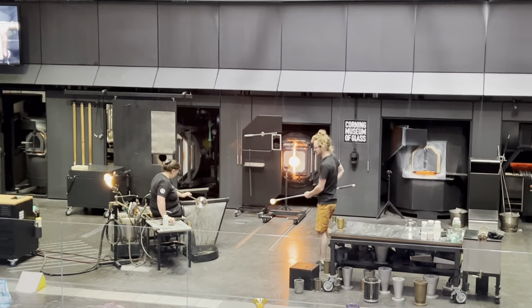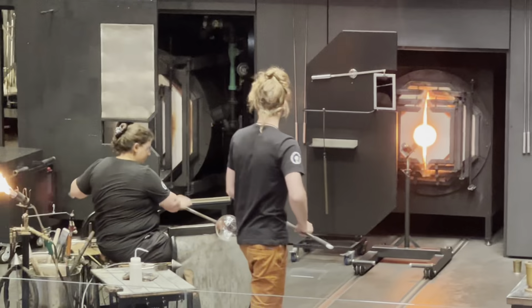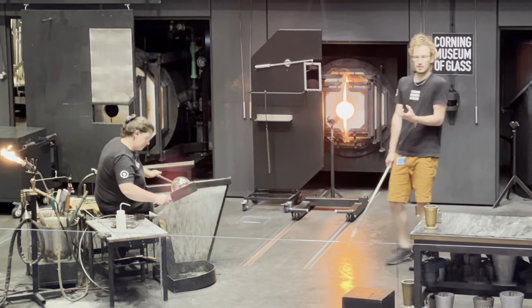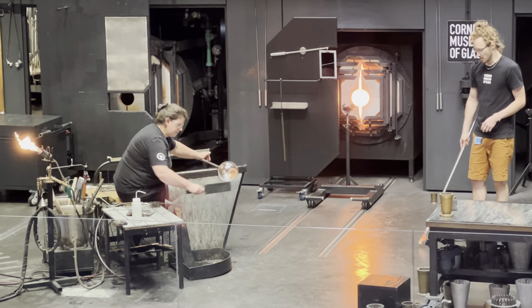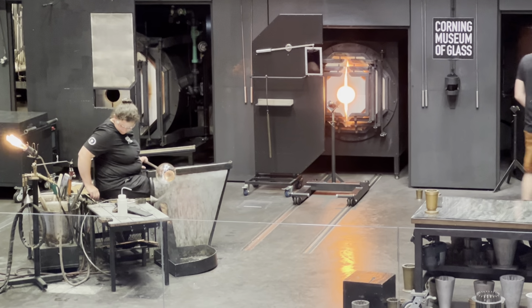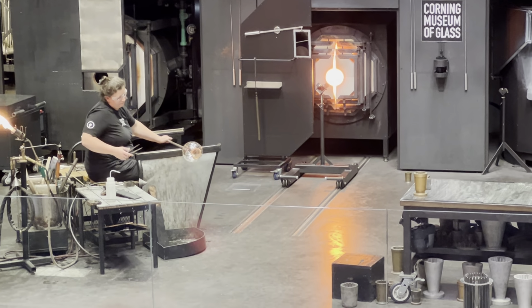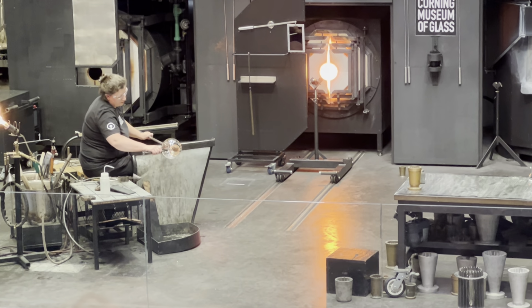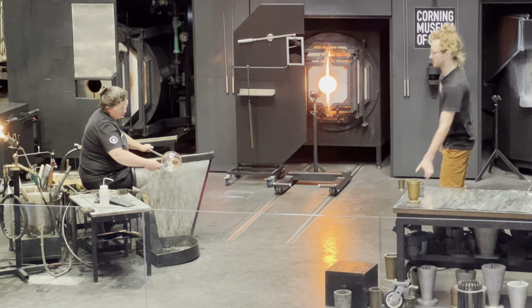It's very clear that it's hot. The bubble that Catherine has doesn't look nearly as hot, but it is still well over 1,000 degrees. And we know this because it's not broken. As glass cools, it shrinks and it contracts. And if that happens too much too quickly, it'll break itself apart. So we rely on our experience, looking at the glass, knowing how hot it is based on the way it moves, what the temperature is.